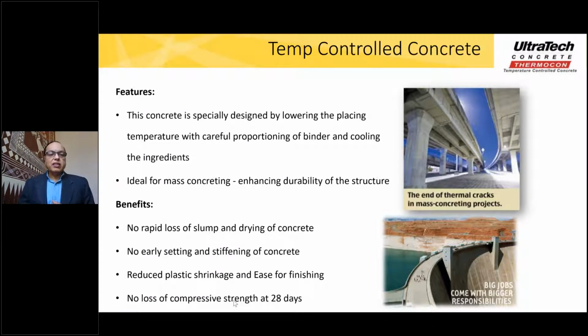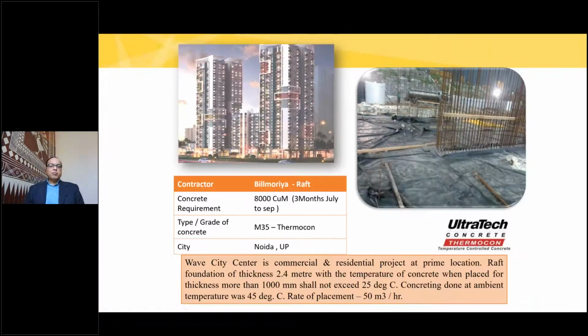The benefit of this is that there is no rapid loss of slump and drying of concrete. There is no early setting or stiffening, there is reduced plastic shrinkage cracking, and it is very easy to finish. And 28 days strength is no issue at all. Now, this is one example of the Bilimoria project where this was used. About 8,000 cubic meters of concrete was used in about 3 months' time, and this was used for M35 concrete. This Bilimoria Towers is in Noida, UP, and it was used in the raft foundation.